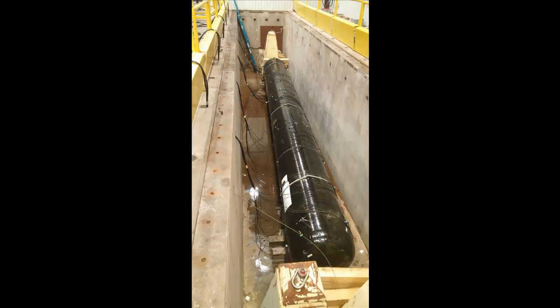The MAE examination was requested due to the composite pressure cylinder being involved in a motor vehicle accident where the composite may have experienced damage. As the cylinder had a higher than usual probability of having compromised structural integrity, pressurization method A of ISO 19016 was selected by the Level 3 overseeing the program. By utilizing the test pressure of the composite cylinder, the structural integrity could be more thoroughly investigated.